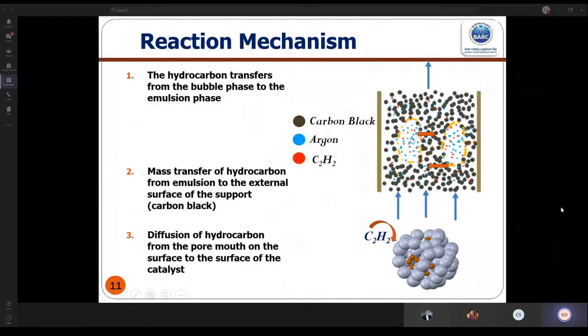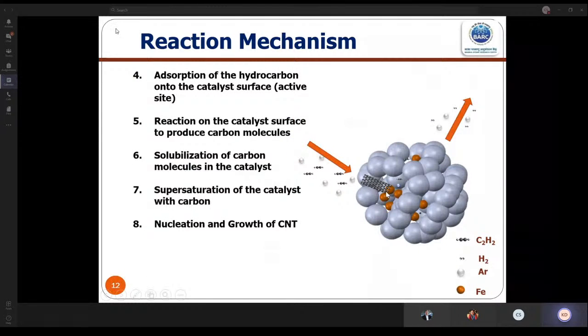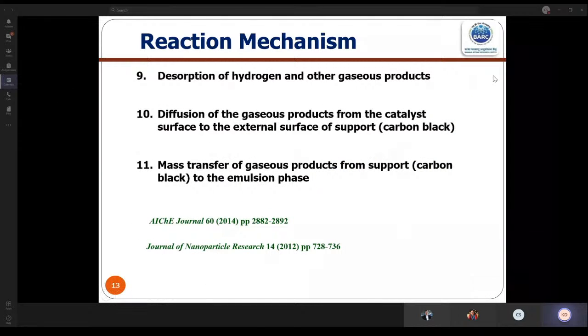From the bubble phase, the hydrocarbon, that is acetylene, travels to the emulsion phase, and in the emulsion phase it interacts with the carbon black particles. It tries to diffuse through the carbon black particles, and here the iron nanoparticles are sitting. When the hydrocarbon comes, it gets cracked, and the carbon has solubility in the iron nanoparticle. It gets soluble, gets saturated, finally supersaturated, and then after supersaturation it comes out as a tubular structure, depending on the partial pressure of the supersaturated species as well as the composition of the gas. And when the carbon nanotube grows, the decomposed hydrogen and the argon come out. So this is the mechanism which is proposed for this kind of synthesis.